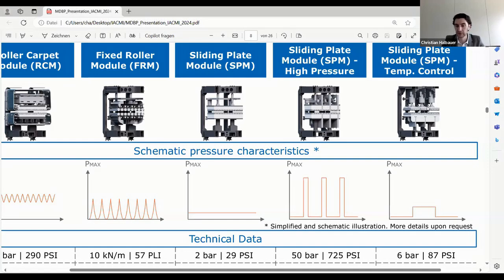so as to make sure, especially for the thermoplast composites, we can adapt to the polymer specific cooling curve. So instead of going with a very high temperature and then immediately decreasing it to a lower one, we can do it step by step gradually.